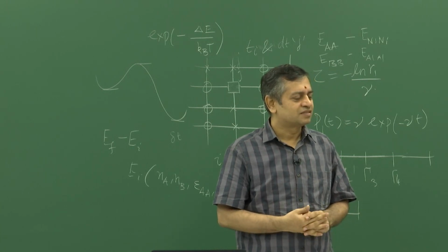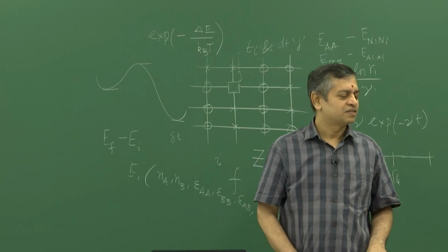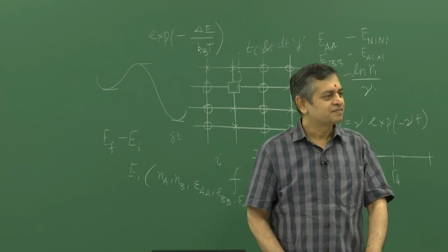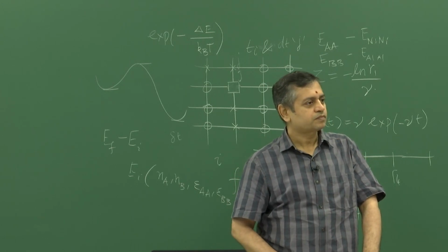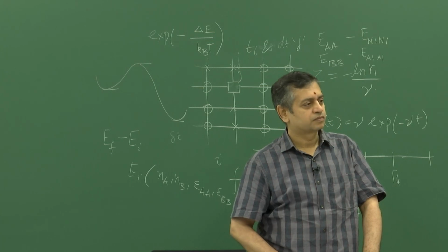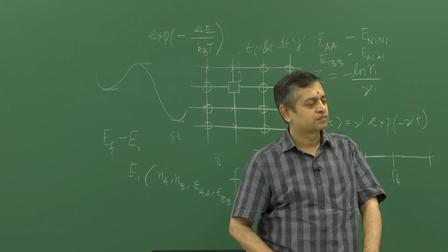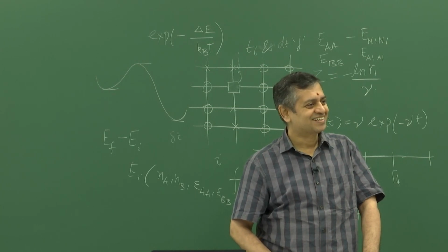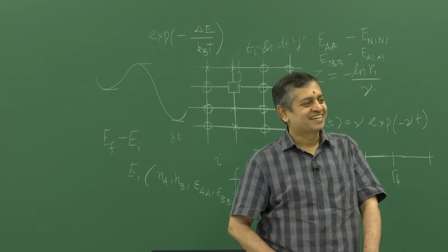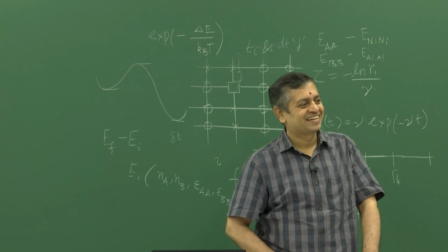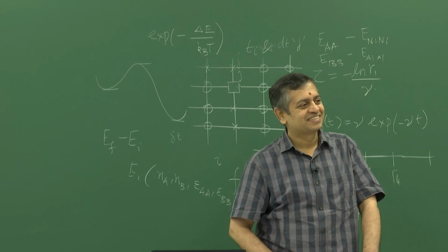I remember that I had certain problems when we did this nickel aluminum system. There are precipitates, they have this ordered structure. So you have one B atom and the next B atom is only on the second neighbor shell, and all the first neighbors are A atoms. So it will not label it as a cluster? Yeah, you have to do it up to second neighbors. But then there are also a lot of random connections. So I tried to modify it so that I count it only if there are more than one, say 2 or 3 neighbors.